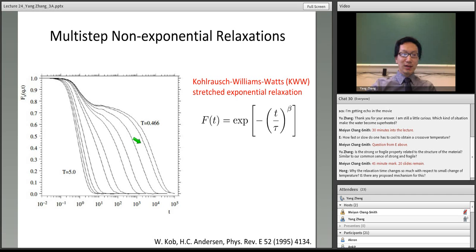For this non-exponential decay, it can often be described with a KWW stretched exponential function. This basically assumes that the relaxation time has a certain distribution. When you measure the system, you average over all the different relaxation times, and you end up with a stretched exponential. In other words, the dynamics of the system is highly heterogeneous. This spatial heterogeneity is also a very important concept in the study of supercooled liquids and the glass transition, so we'll talk a little bit more about it in the next few slides. This intermediate scattering function also provides us an insight into what is going on at the atomic level when supercooled liquid forms the glass.